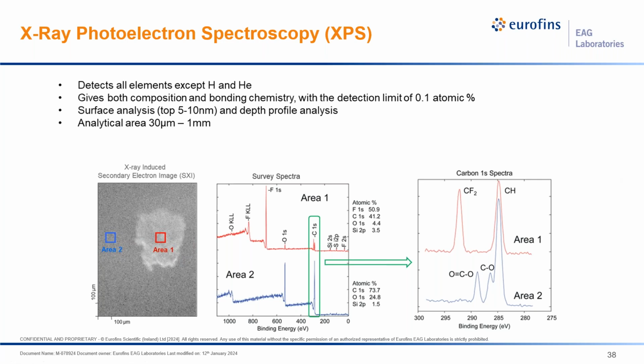In our SEM, we have a secondary electron image. We have that in Auger. For XPS, we have a secondary electron image that's generated by the incident X-ray beam, so it's called an SXI. All of those are used to get a visualization of the surface so we can select locations, identify, say, contamination locations on the sample. Survey spectra, so these things can be run just like the Auger point mode, line scan mode, mapping, all of the fun stuff.